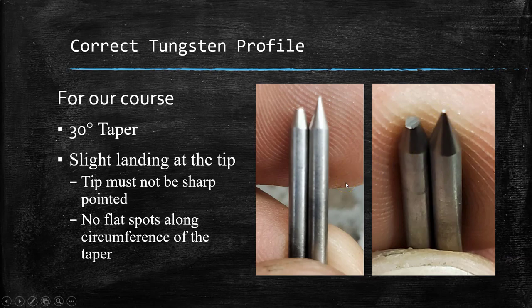Also, as you're grinding your tungsten, if you hold your tungsten in one spot just too long, you're going to develop a flat side. So as you're looking all around the tungsten along the circumference, it should be smooth all the way around. If you see any areas where there is a flat spot, you need to regrind your tungsten, because that's going to affect the welding arc.